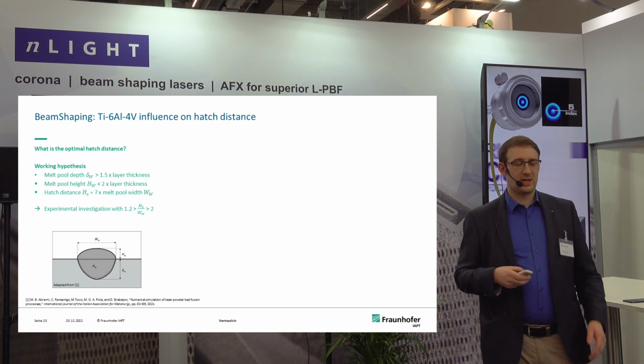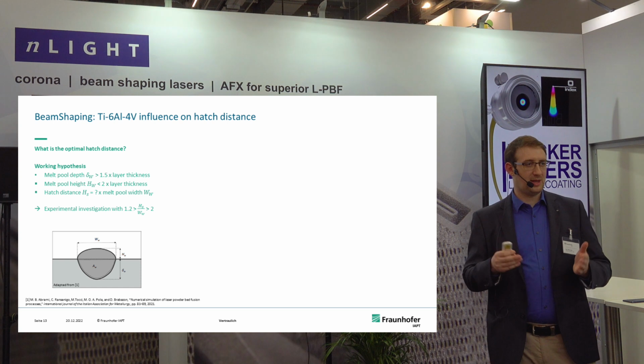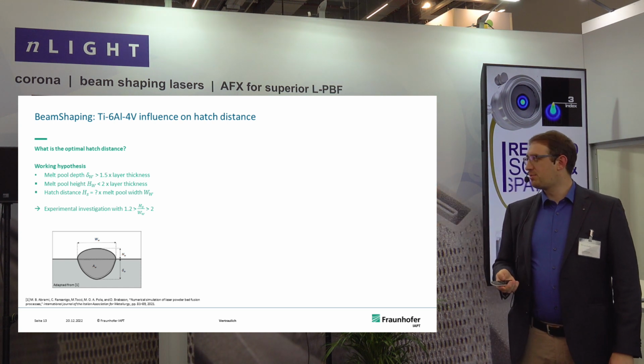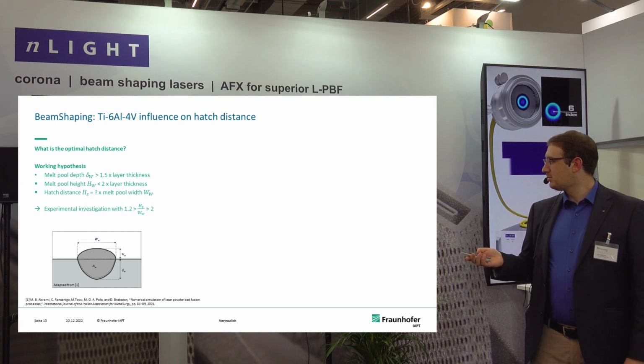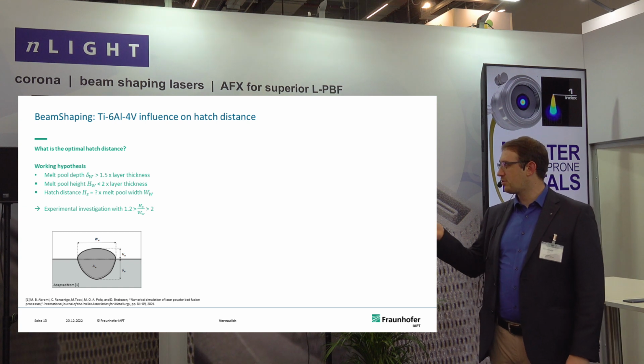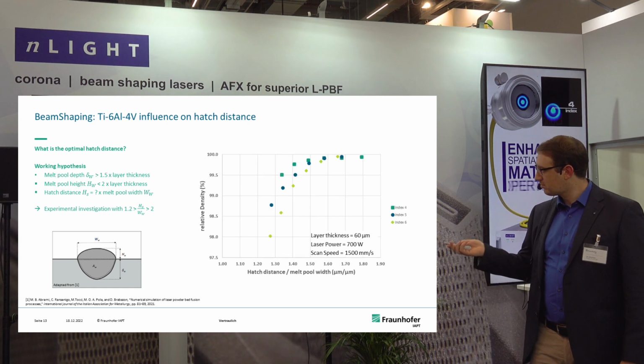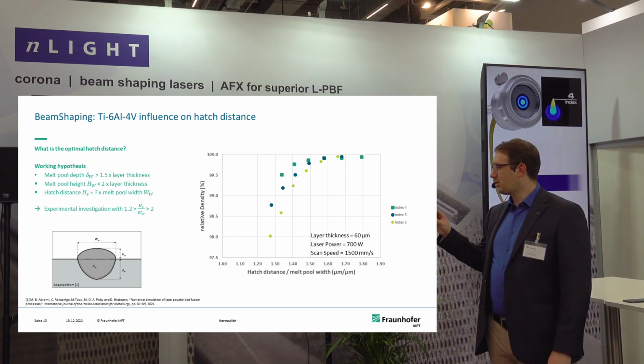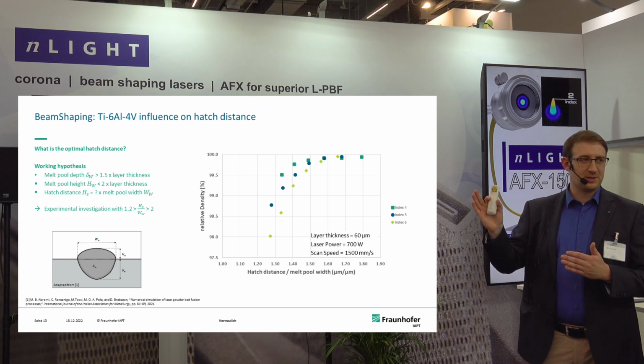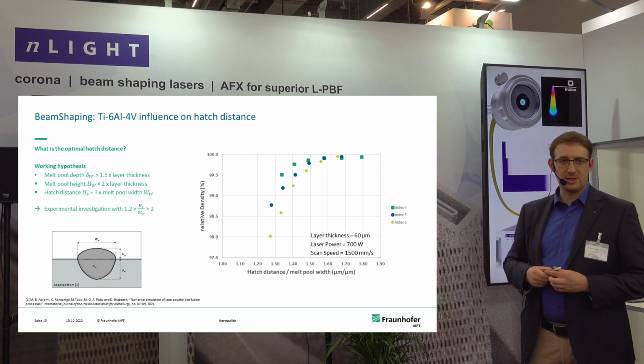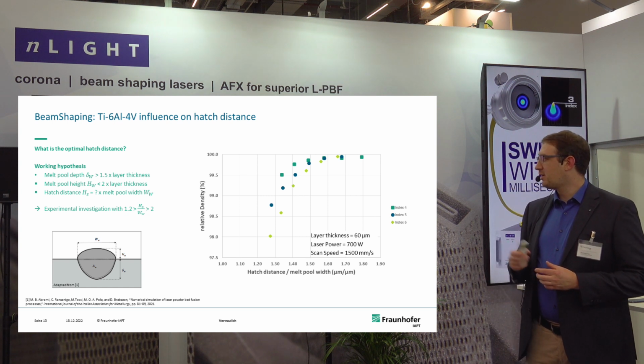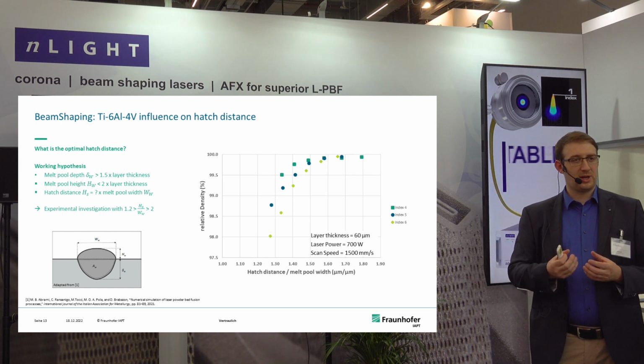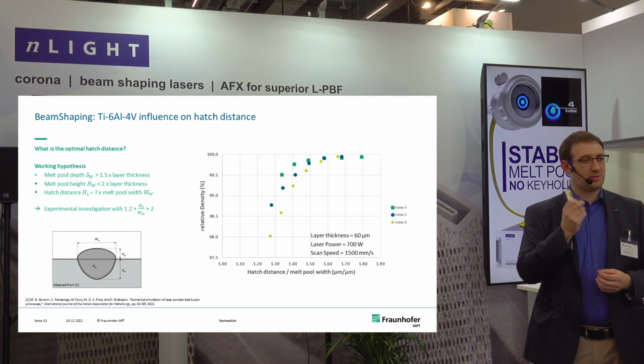So then we made an investigation for the hatch distance depending on the melt width, excluding all parameter combinations that were not suitable. If we're looking at the density for this ratio of melt width by hatch distance, we can see here, to the left, we have a bigger hatch distance compared to the melt pool. And in the different colors, we see the different indices of the nLIGHT laser. Quite surprisingly, for us at least at first glance, with index 4, the beam profile where we have a comparatively big part of the Gaussian profile in the middle, we actually have better results.